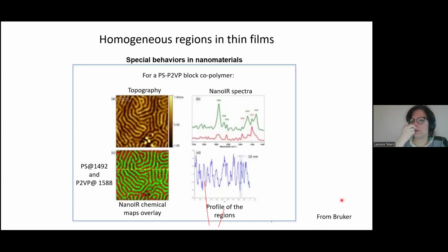So after doing a lot of these developments in my lab, we also started working with commercial systems, and we started exploring some of the applications that would be interesting to touch with this platform. So at the very beginning, the applications were on polymers. So here, polymer scientists were developing block copolymers where you have two different regions. And then by putting the tip on one region and the other, we could see that we detect the differences in chemical composition of the two spectra, even though the size of the region is in the nanoscale range.